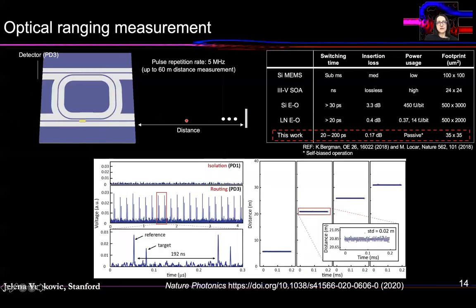And we use this circuit to perform ranging measurements for up to 60 meter distances. It is important that we can do it with very high speed, and we can also do it with very small insertion loss. It's fully passive and has a much smaller footprint than any of the other electro-optic switches and modulators that people have used for similar applications recently.